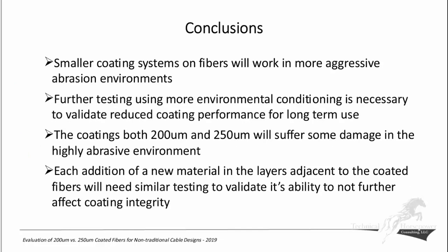And basically, the conclusions we've come to are that these smaller coating systems on the fibers will work in these very aggressive abrasion environments, as well as the 250, but way better than the legacy fibers. But we do need to do further environmental conditioning to validate long-term use. I think it would be important to see how we could do a temperature, humidity, or even a salt spray test. Both the 200 and 250 suffer in these very abrasive environments.